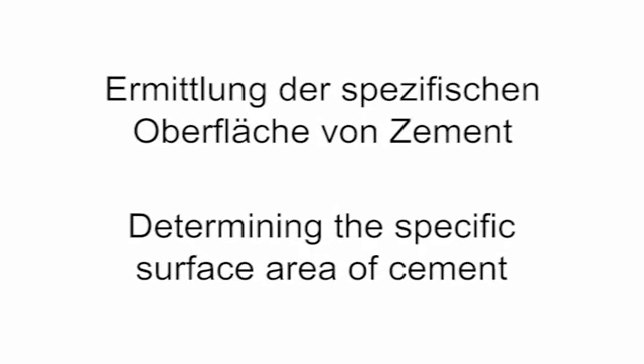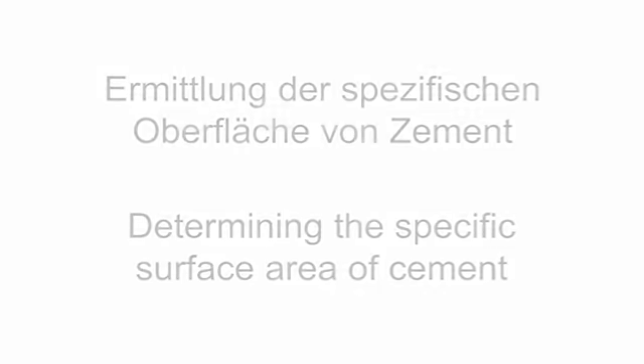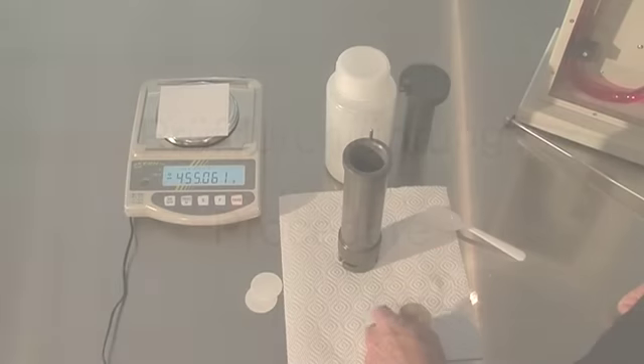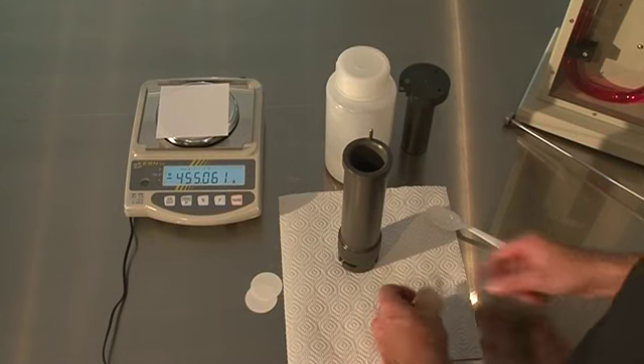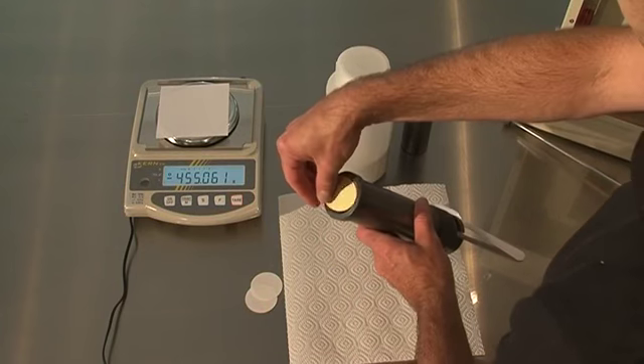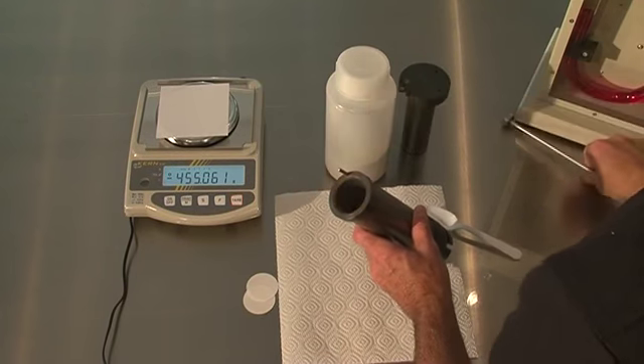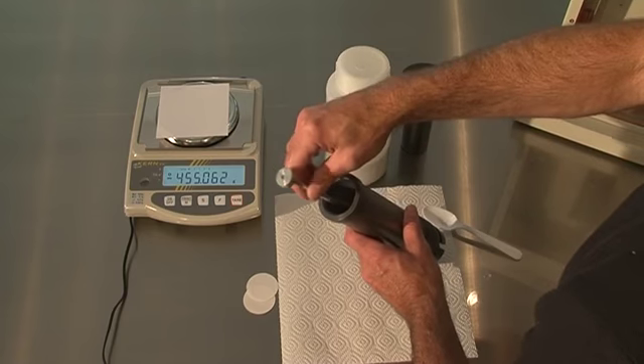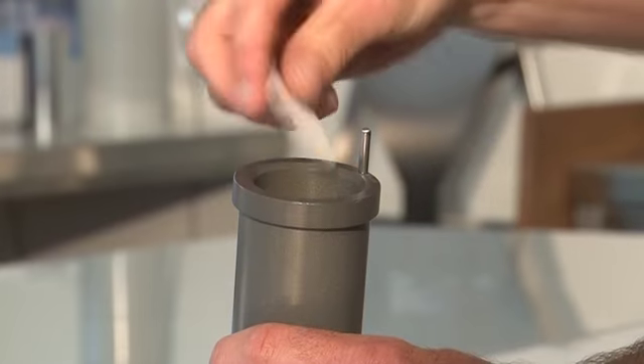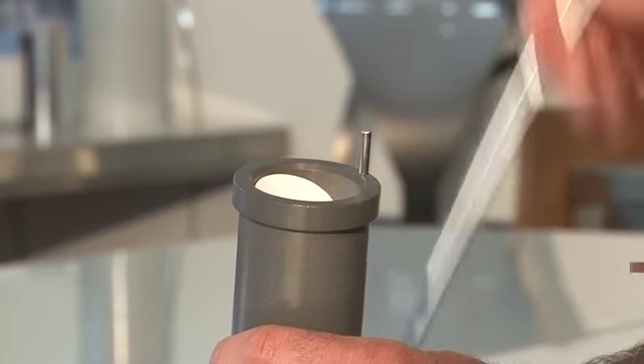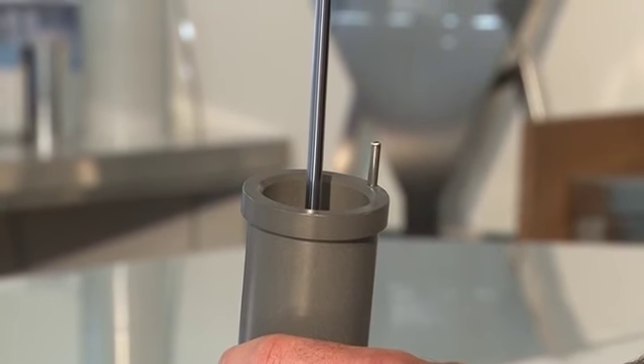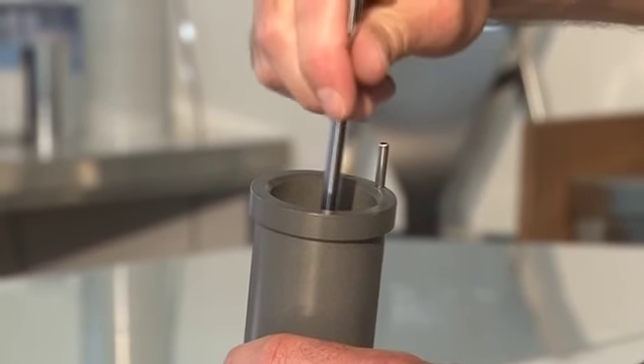Determining the specific surface area of cement. Procedure. Using the example of cement, a grinding fineness test is carried out by Blaine. First, a perforated disc is inserted in the measuring cell and pressed onto the lower edge with the tamper. Then, a paper filter disc is inserted and pressed onto the perforated disc.